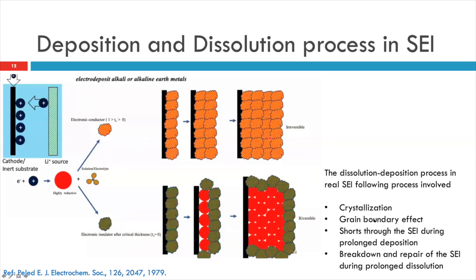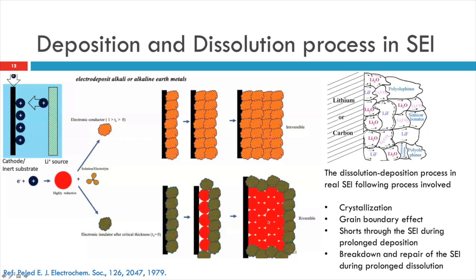If it is an electronic conductor, it has been shown that the further deposition from the electrolyte decomposition is very uniform, and it ceases after some time. And if your surface film is an insulator or a mixed insulator, then the deposition of lithium is not uniform, and then there will be growth on the lithium metal. That shows that if your surface film is insulating type, you have a probability of forming dendrites.